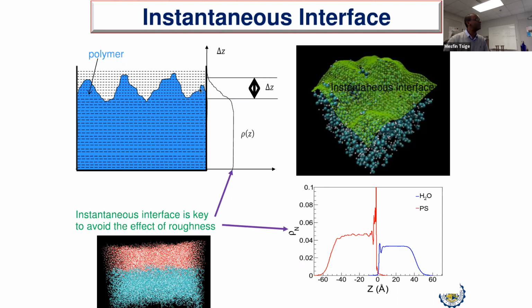The reason being, when I get closer to this one, I have areas where I don't have polymer. So I end up dividing by the same volume, instead of dividing only by the volume taken by the polymer atoms or groups. So as a result, we see this kind of tan hyperbolic. We found that this hides most of the information that we need.